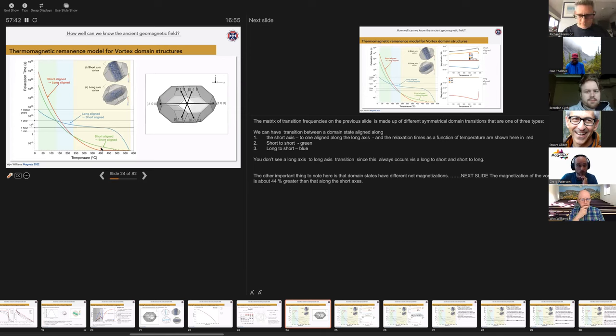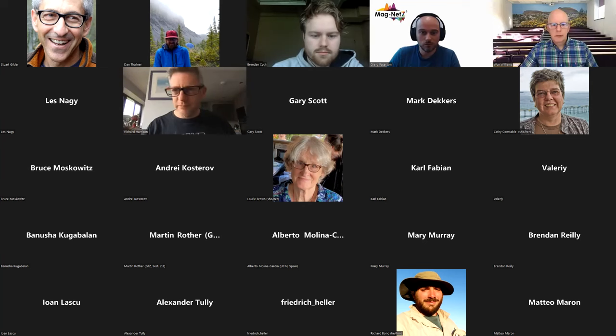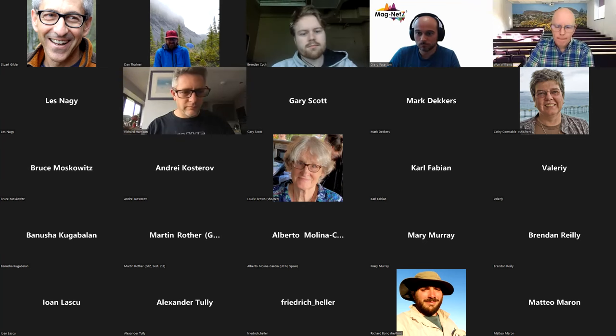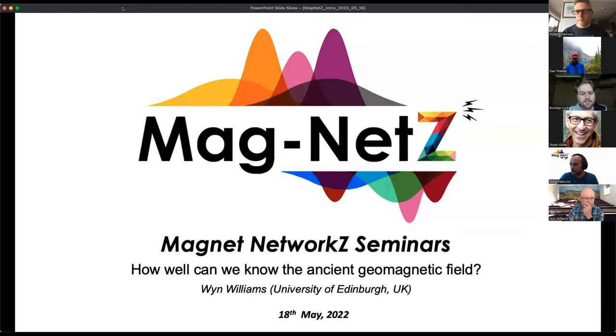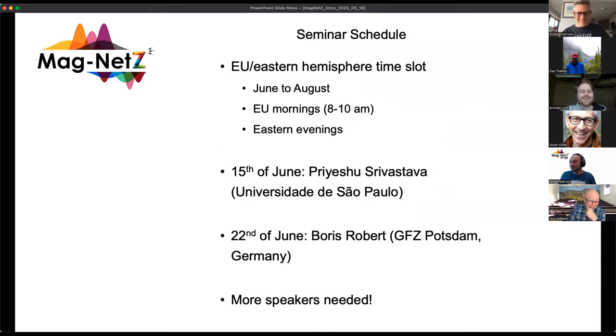So this effect, although we've chosen it because we knew it was going to have two different domain states that were stable in it. I think the effects that we see should be replicated in any grain that has different domain states of similar energies in it. If you have a minimum energy state that is much lower than other possible domain states throughout its temperature range, then you won't see these effects. So the question is how frequent are these types of grains? And, as I said, people have got paleointensities, including you, that we think are reasonably good. But, you know, we all know that it's not unusual to have paleointensity failure rates in high percentages. Many of those are chemical alteration. Sometimes chemical alteration is indicated by these PTRM failures. We've shown here that PTRM failures don't have to be because of chemical alteration.